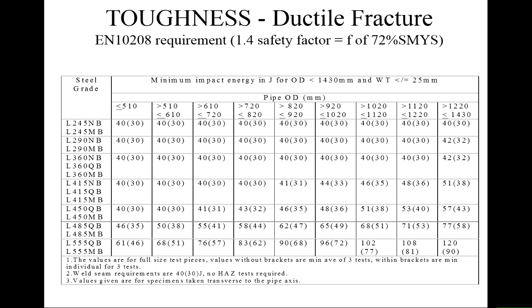So you go and look at the standards. So this is the EN standard, and you've got a minimum impact energy in joules for original outside diameters of the pipe less than 1.43 meters, and wall thickness less than 25 millimeters. So you start to see that you get different tables with slightly different conditions. You'll see the values for full-size test pieces. And you've got two things here. You've got the average value to start off with, and in brackets you've got the minimum value.